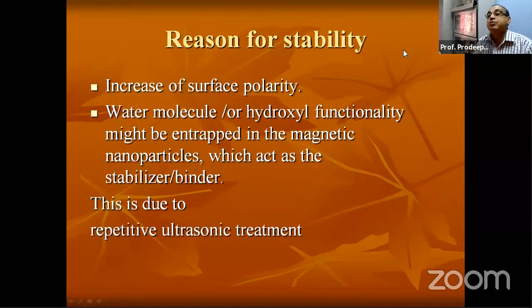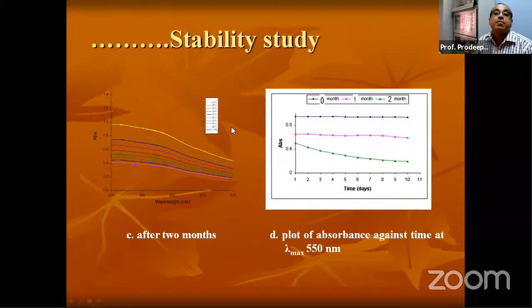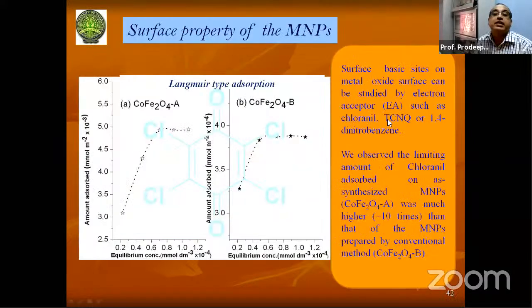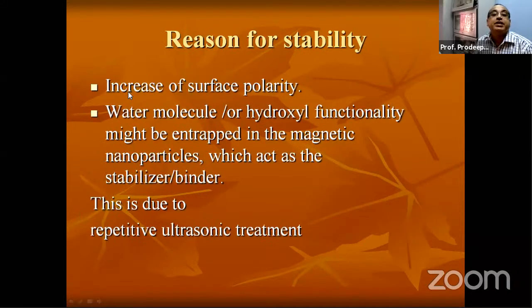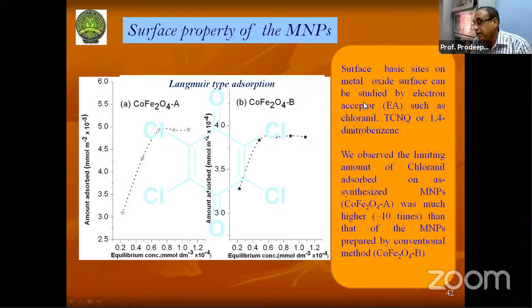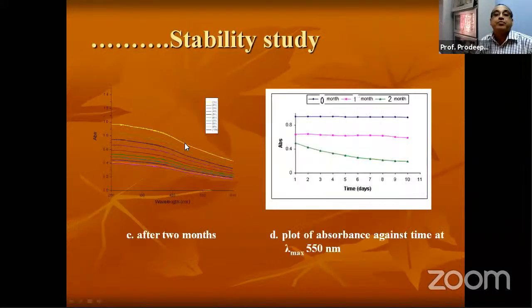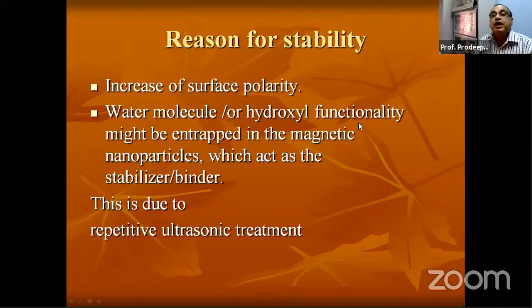So now the question is why it is so stable in aqueous or alcohol medium. So this is the aqueous solution. Now we see an increase of surface polarity. So when we reported this, we must prove that it has very high surface polarity. So this particular explanation shows that this cobalt ferrite nanoparticle has very high surface polarity. And secondly, water molecules or hydroxyl functionality might be entrapped in the magnetic nanoparticle, which acts as a stabilizer or binder. So that is another reason maybe.